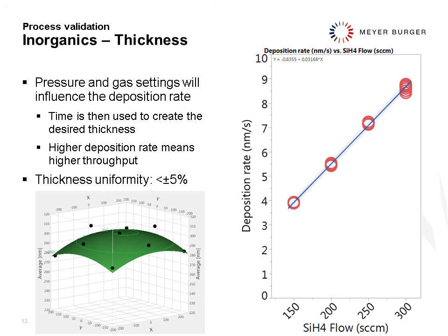Now, looking at thickness, for example, we give also some freedom, meaning that it is possible to change the pressure and the gas settings to influence the deposition rate. Well, the deposition rate together with the timing will give you the thickness, but it will also give you the throughput. So that's why I bring here the deposition rate instead of the thickness. About thickness, of importance is its uniformity. So we have an example of uniformity of plus minus 5%.